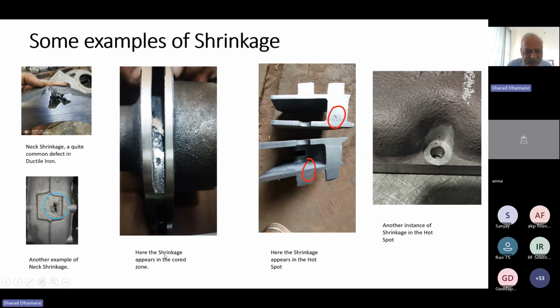Then in some, the shrinkage appears in a core zone. Now why it happens in core zone, I think we will take up in the next webinar when we specifically discuss defects and their mechanism. But here, I would like to mention only that core zones, when casting geometries are in such a way that the core is thin and the casting sections are thick, such geometries and such part designs are quite prone to shrinkages in core zone, impellers, for example.